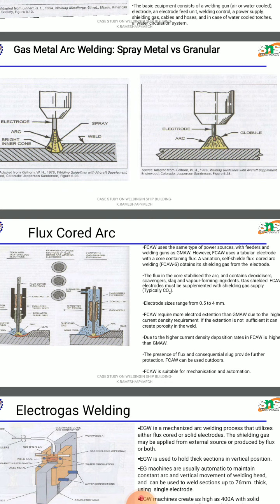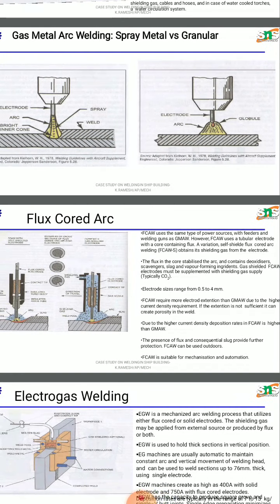Electrode size ranges from 0.5 mm to 4 mm. Flux core arc welding requires more electrode extension than GMAW due to higher current density. If the extension is not sufficient, porosity can be created due to high current density. The presence of slag allows the product to be used outdoors.